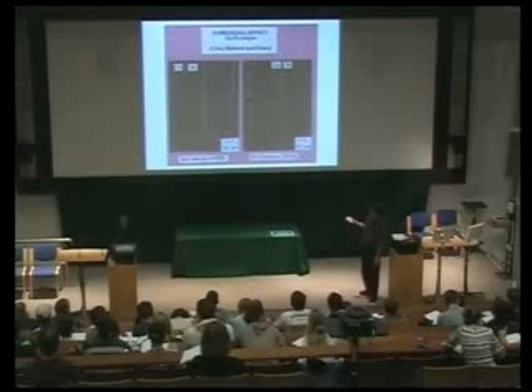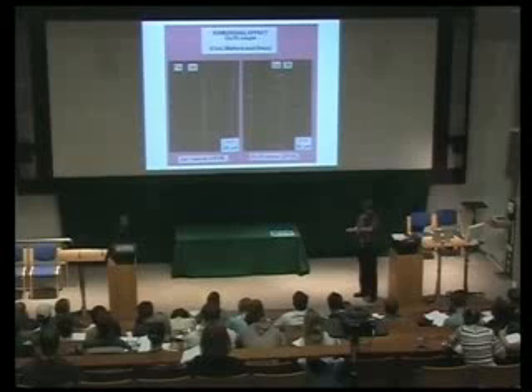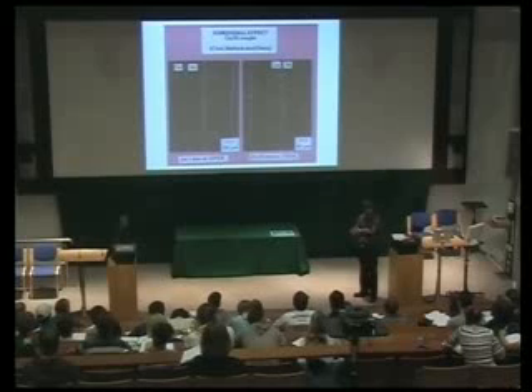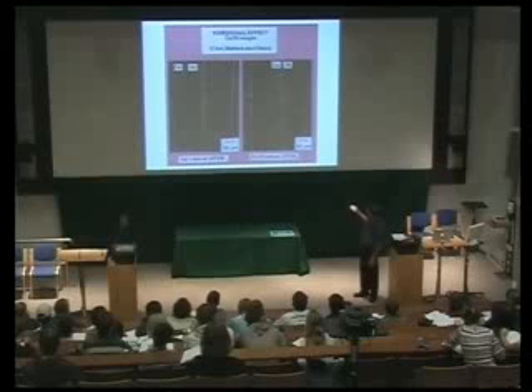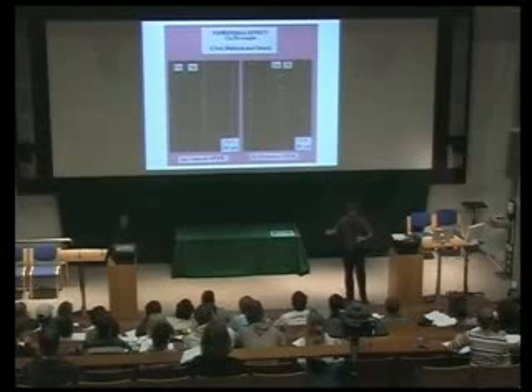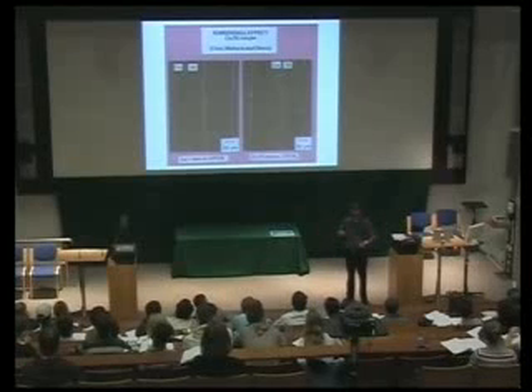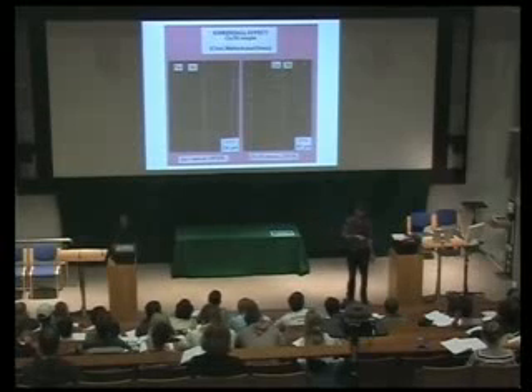The other consequence of this, in this case we are looking at copper-nickel couples, is that if you have a greater flux in one direction than in the other, then there will be a greater flux of vacancies in one direction than in the other. And those vacancies will condense to form holes. So you can see after this has been annealed to get diffusion, you get lots and lots of holes in the copper regions, which absorb a lot more vacancies. Because the flux of copper is greater than that of nickel, you end up with more vacancies in the copper region, which condense as holes.